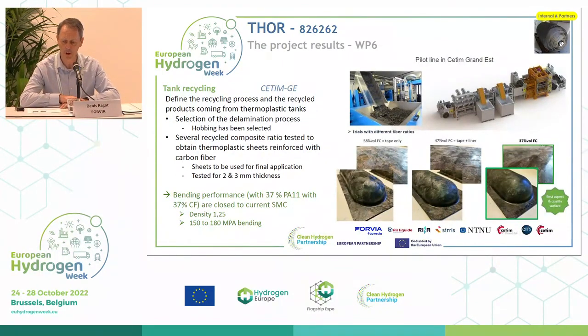The technology chosen was hobbing by the CETIM Grand Est, so that they can make some small parts of the composite, put it on the mold and make a sheet on it. That was the first step, but it is not enough to have a product. You have to look at what you can do with it, and they made some transformation tests. You can see the picture below. And so with the reinforcement of 37%, they have got a good material aspect, and performances are equal to the current SMC, which is a good point.